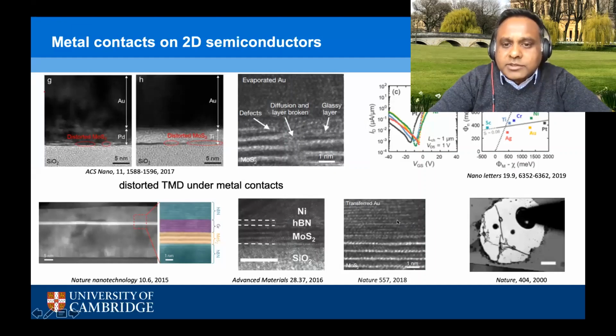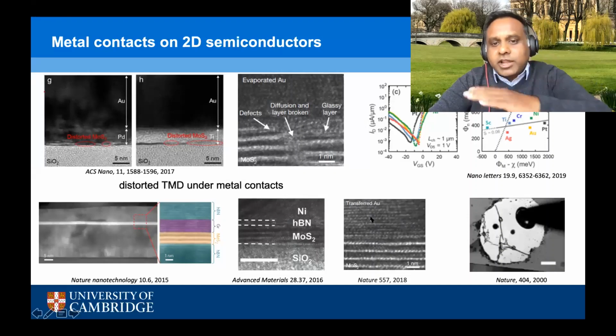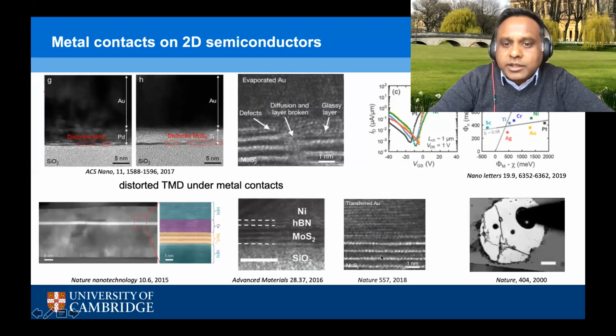There was a recent work done by Duan's group where they showed that if you simply mechanically transfer gold onto MoS2, one can make very good contacts. There's been very old work done that showed that indium, which is a very soft metal, can make very gentle and good contacts to molecules.